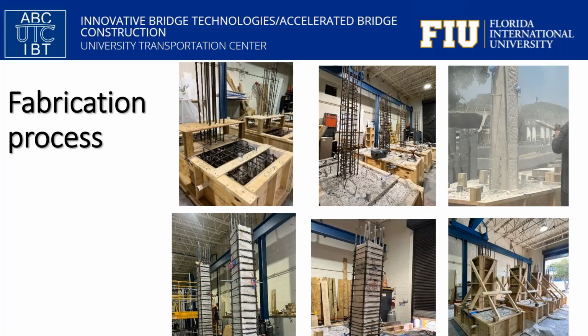First, the reinforcement cage for the footing were placed inside the footing formwork, and then all the longitudinal rebars of column, including those for the core and jacket, were positioned inside the footing. The footing were then cast with normal strength concrete. The next step, the stirrups of core were placed and the cores were cast. For the retrofit specimens, the surface of the core was roughened by sandblasting to improve bonding with jacket. The jackets were then cast, one with normal strength concrete and 2 with open source UHPC mix.